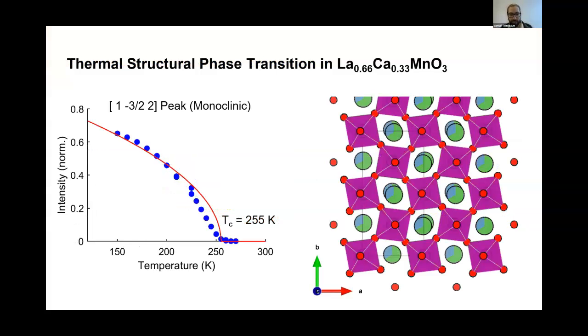So we took this sample to Argonne National Lab and cooled it down and did these experiments now with an X-ray probe. And what you can see is that there's a structural phase transition on top of, again, the unit cell doubling that's associated with the charge ordering.